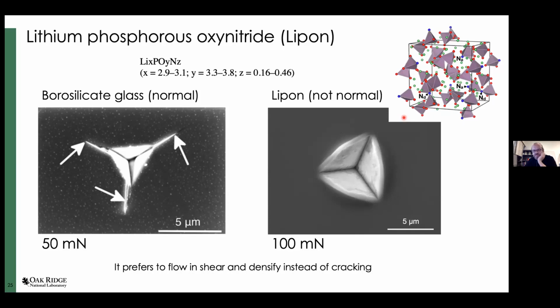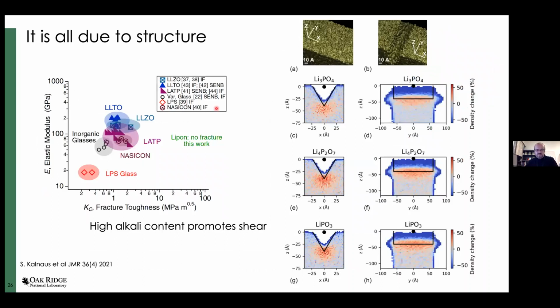It doesn't have a rigid structure. The phosphate tetrahedra are relatively free to move around in this almost a soup of alkali ions, of lithium ions. And they're relatively free to slide with respect to each other and deform bond angles. And the amount of nitrogen that connects those tetrahedra is relatively small. So it allows it to deform without producing any cracks. And this is kind of a summary of where LiPON stands compared to the other electrolytes and commercial inorganic glasses, comparing the fracture toughness and its stiffness, elastic modulus, taken from different references and from our own work.